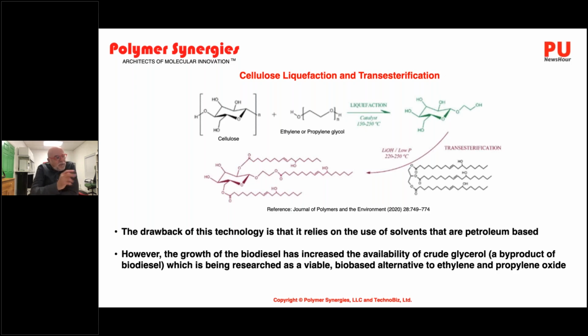The drawback to this type of technology is that it relies on the use of solvents that are petroleum-based. That is changing as research continues. For example, the growth in biodiesel has increased the availability of crude glycerol, which is a byproduct of making biodiesel, and it's being researched as a viable alternative for ethylene and propylene oxides. So there are polyols that are available based on cellulose, and this is the method of how these materials are made.